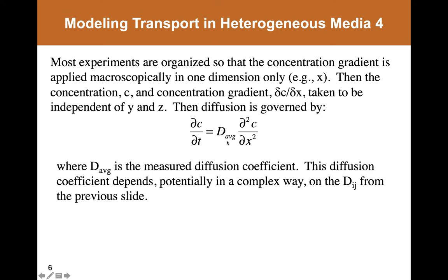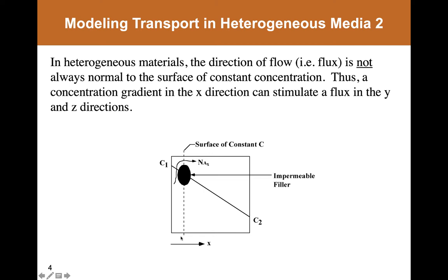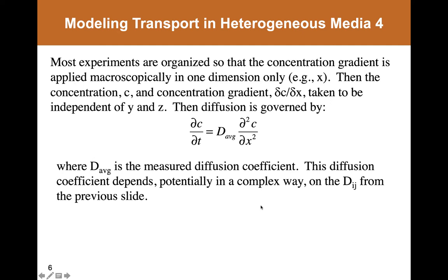That is, if you measured the gas flux or penetrant flux through this material from one side to the other, the flux that you would measure would reflect an average of the transport properties through the entire material, through and around these heterogeneities. And so what's available experimentally is always some sort of average diffusion coefficient, and it would depend in a complex way on these diffusion coefficients in the various different directions.